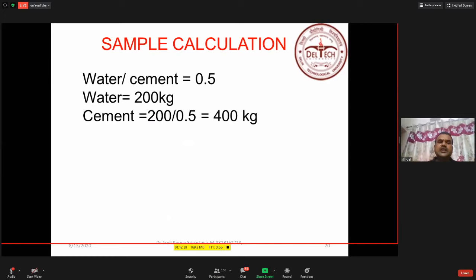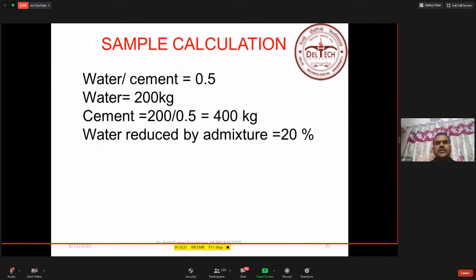Now the role of chemical admixtures comes. So now we add the chemical admixtures. In the market, if you see, there are different generations of chemical admixtures. That is called a super plasticizer, or it is also called a water reducing admixture. So some admixture is giving you the water reduction of 20%. Some admixture is giving you the water reduction of 35%. Some admixture is giving you the water reduction of 40%. Or sometimes by varying the percentage of these admixtures, you can increase or decrease the water reductions.